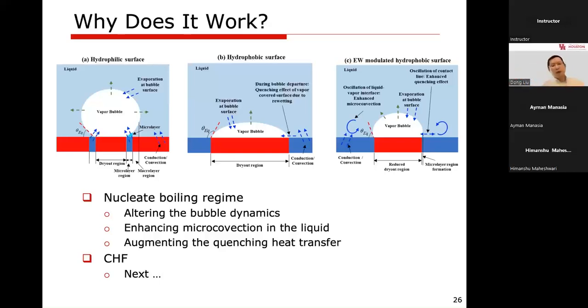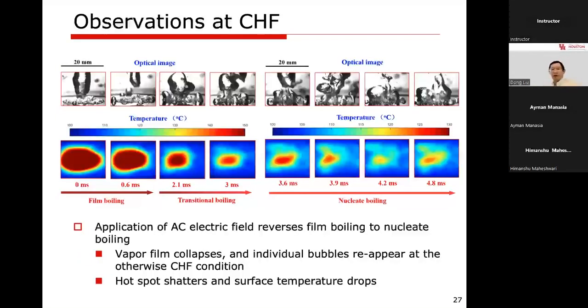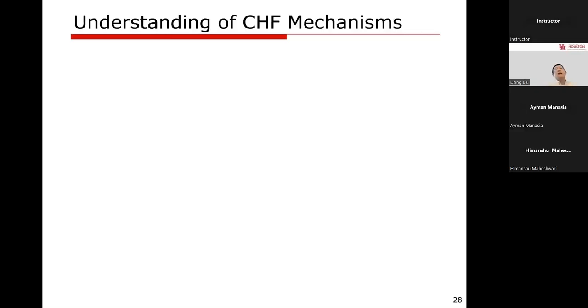Now, the bigger problem is how does electrowetting enhance the critical heat flux? Okay, so for that we developed a model. These two sets of images tell you in detail what happens with electrowetting when the heat flux reaches CHF. So the first set of images are from the optical images. So you see clearly the disappearance of the vapor film and the reappearance of the vapor bubbles. Now the second set of images tell you the temperature. So these are the observations. Now behind that, we need to understand what actually contributes to CHF. So there are two.